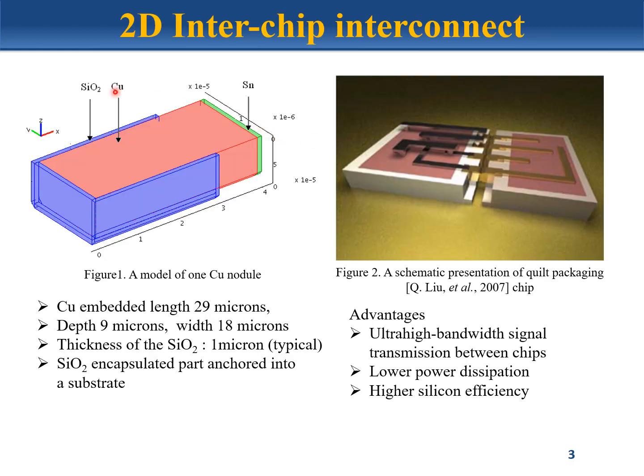On this page, we're going to be talking about the quilt packaging method. On the right side here, we can see that there are two silicon substrates with copper traces and nodules sticking out from the side. These nodules are basically copper blocks that are extending from the body of the silicon substrate and then interfaces with other nodules from other silicon devices. These are very efficient at ultra-high bandwidth signal transmission and causes low power dissipation and has a higher silicon efficiency.